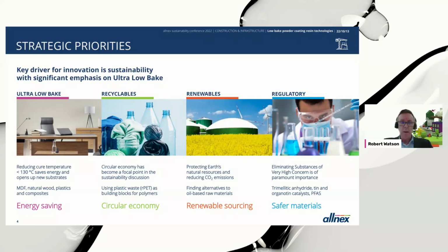And the reason why powder coatings at 130 degrees centigrade is important is it opens up two avenues that weren't available before. One is that at 130 degrees centigrade, we can start to bring in the non-metallic substrates like MDF, natural wood, plastics and composites. And what this does, it enables powder coatings to have a greater reach. And it gives the applicator and the fabricator a wider choice of technologies than they currently have. So where they may have used a solvent-borne liquid coating, powder coatings can now come to the fore.